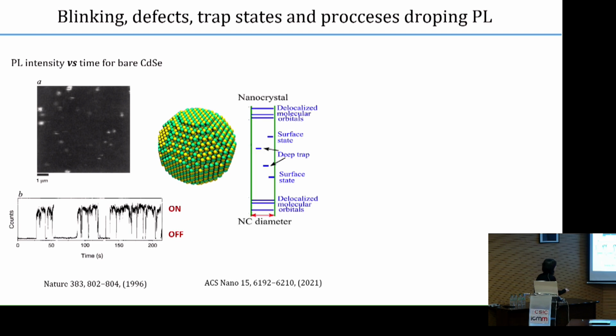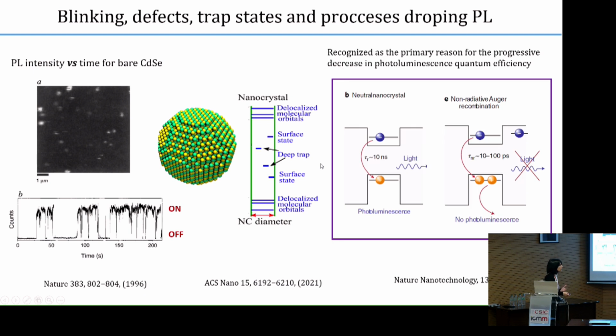Of course, this comes from the fact that the crystal is not perfect, and has a lot of surface and other defects that yield surface traps and deep traps. If I have a perfect crystal, what I have is a normal photoluminescent response in which one electron moves to the conduction band, leaving a hole behind, and the recombination of this electron-hole pair emits light normally. But with these deep and surface trap states, our crystal is forced into different processes that kill this luminescent response.